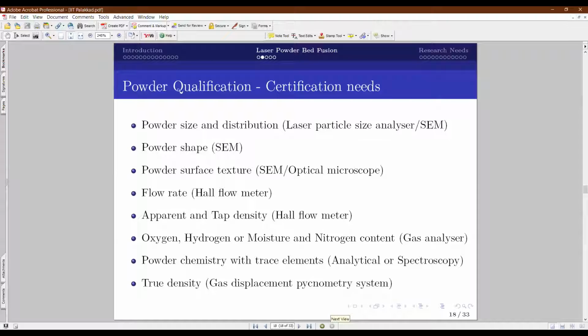How do I ensure that the part is airworthy? So I will start from the feedstock, that is the powder. These are the properties I will check and freeze. That is very important, because only when I freeze it can I ensure consistency in the next batches. For example, size distribution, shape, surface texture, flow rate, apparent density, tap density, all the gaseous elements, powder chemistry with the trace elements, and true density. We also specify the instrument used to get these properties. We freeze each and every parameter, and unless each batch or each lot meets this freeze requirement, it is not allowed to be used to build a component.